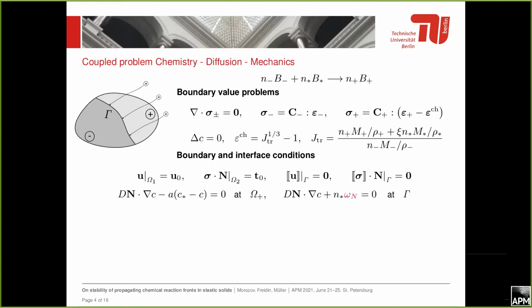We consider a sharp interface, the chemical reaction localized to the sharp interface. We assume that our material star diffuses through the material plus, and the reaction occurs at the interface between materials plus and minus. So far, we assume that all the material star which has diffused to this interface is consumed by the reaction. This chemical reaction is accompanied by the chemical transformation, and so far we utilize the chemical transformation model, which can be controlled by parameter C here, and can be utilized as a so-called solid skeleton approach, or another limiting case. So when we fit our experimental data, we choose somewhere in between, because we are not sure what is actually happening there.